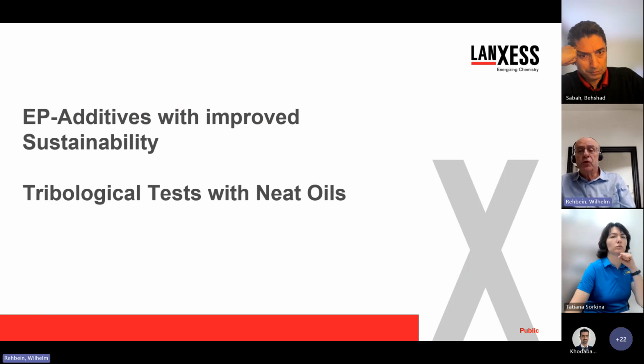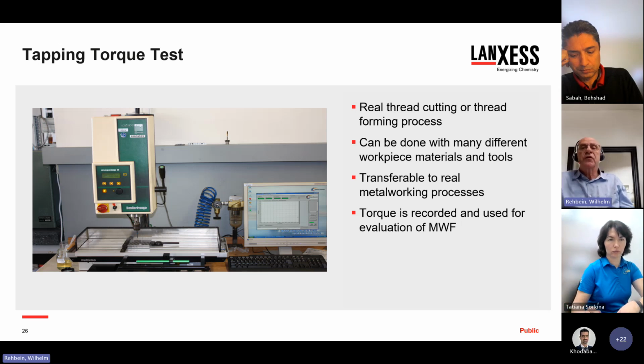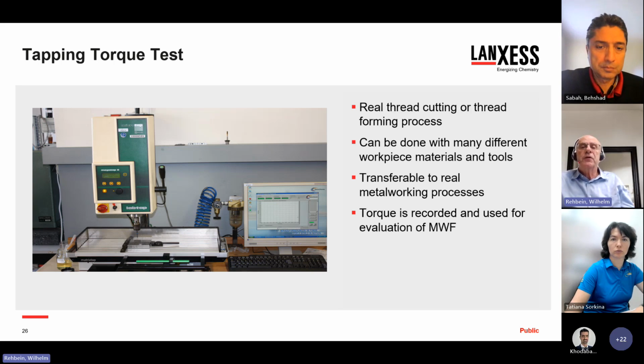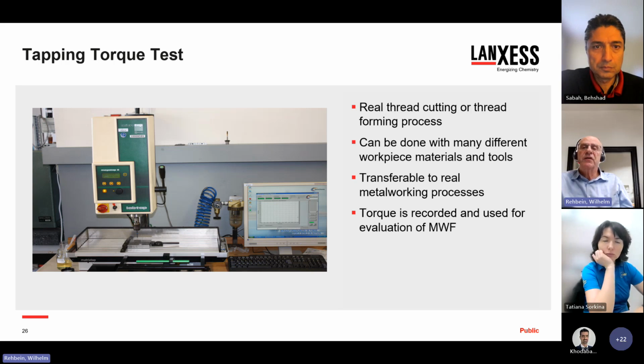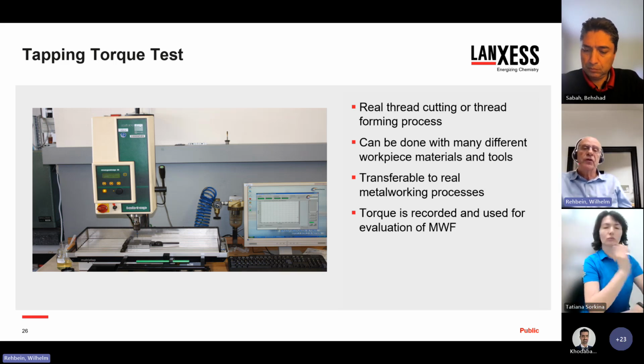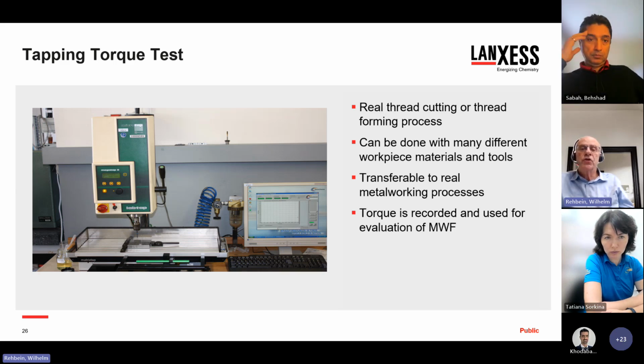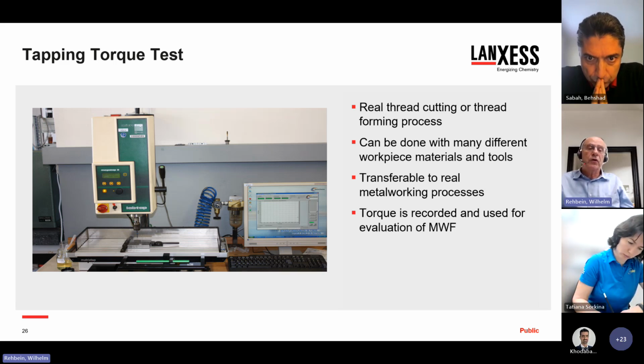Now I will come to some tribological test results, first with the neat oil formulations. We use the tapping torque test to evaluate the performance of the different EP additives. This test uses a real thread cutting or thread forming process in which the torque is recorded and used for the evaluation of the different metalworking fluid formulations. It can be done with many different workpiece materials and also different tools. The test results are very well transferable to other cutting or forming processes. A lower torque indicates a lower energy consumption in the process, and it also results in lower tool wear.